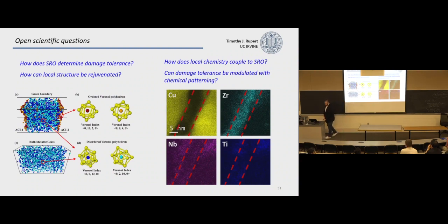So we think this is actually connected to the local environments that these elements like to be in. If I study copper niobium by itself, it forms an ordered segregation pattern. So it kind of makes sense that the niobium likes to be in these ordered packing motifs. But we think we can tune this and control it to be able to engineer these local short-range order patterns and tune these responses.